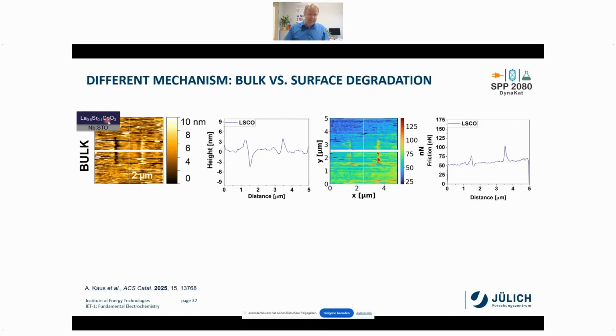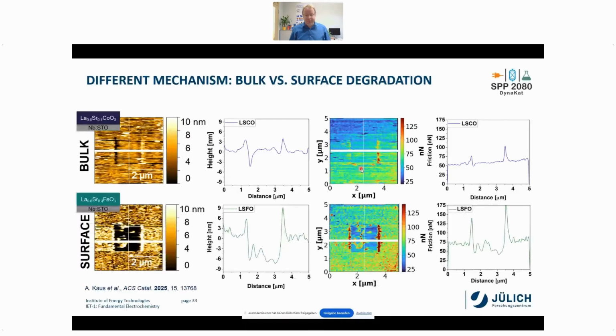So in the case of LSCO, we see this square here in the middle where we scanned before, we zoomed out, but there's not much change in the height. We can see the borders, but there's not much change in the height level. And also in the friction channel here on the right, we see that the color is basically not changed within this part. So what that means is that we get a bulk-like degradation throughout our material, and there's no surface film. However, for LSFO, this completely changed.